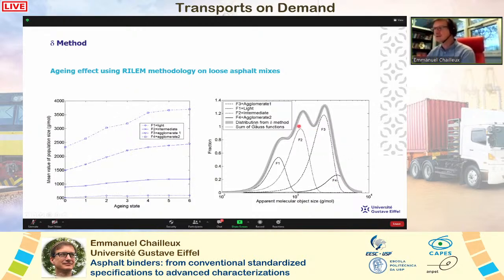and we can follow these populations according to aging state, and we recognize the result we have also with the size exclusion chromatography. It means that nothing happens for the lower molecular mass, but what is very important during aging is the increase of the highest molecular population, certainly due to some association of molecules during aging linked with the increase of polarity of the medium during aging. It's a typical result we find with the delta method, which is very well known using conventional methods.